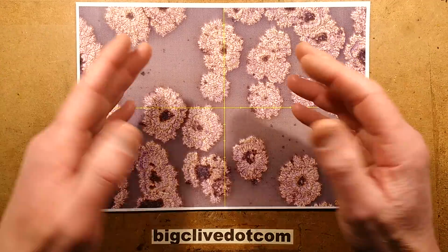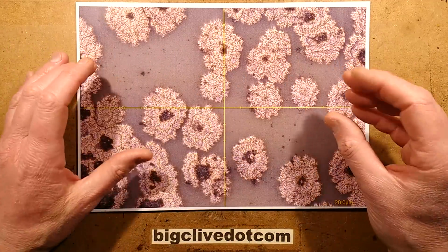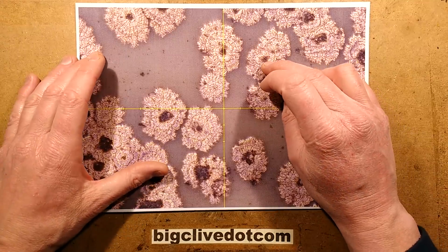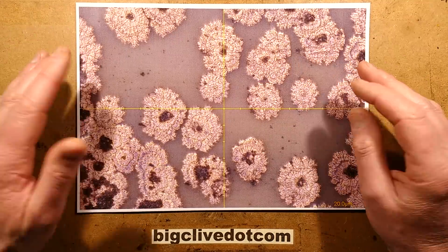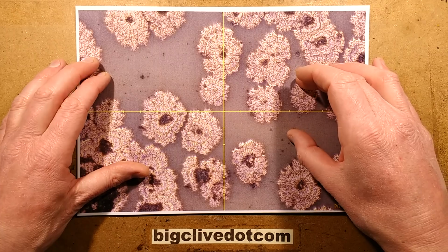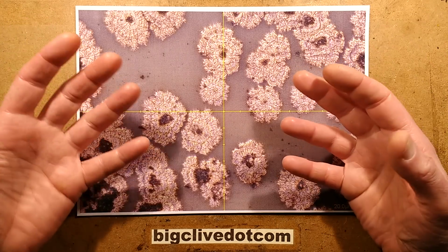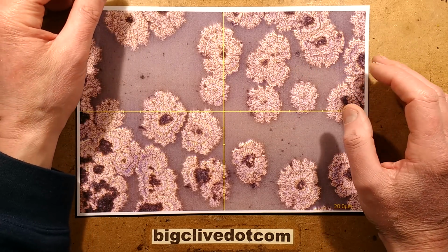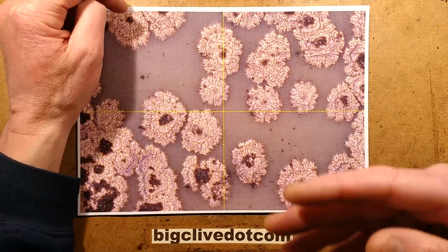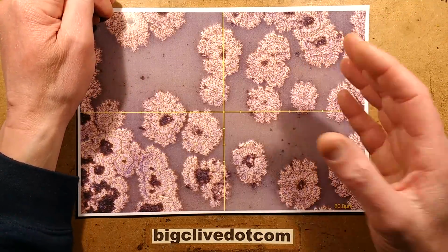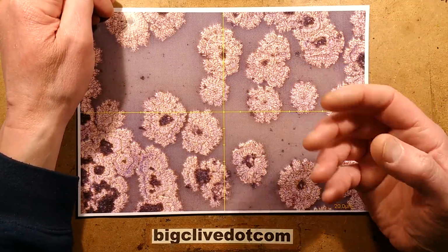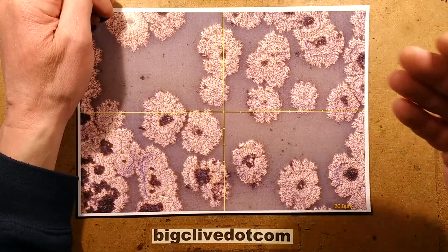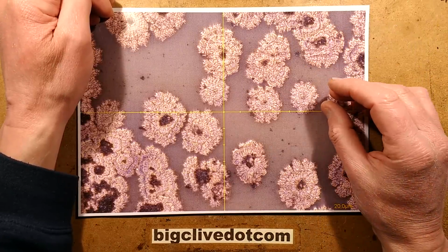And it showed from the pictures on this side and the other side that the copper has perforated and plated through. It's basically made a plated through hole through the separator. And that's basically conductive. It means that when you try charging the cell, it's going to leak current through that. And in this case, it would leak an awful lot of current. It would be pretty much draining the current that you were putting in. It would basically be passing straight through the cell.